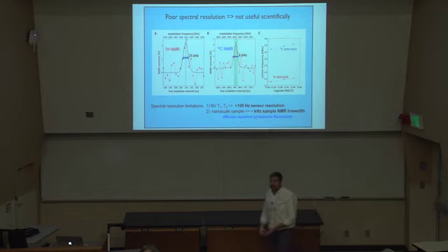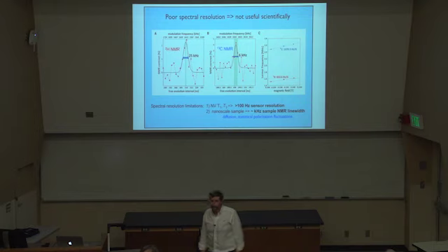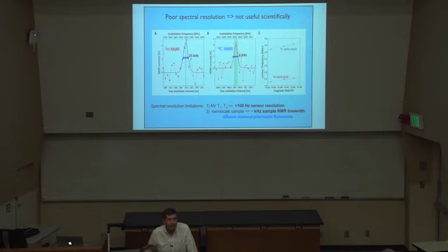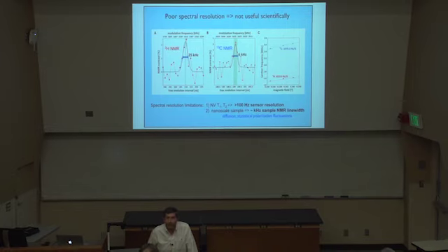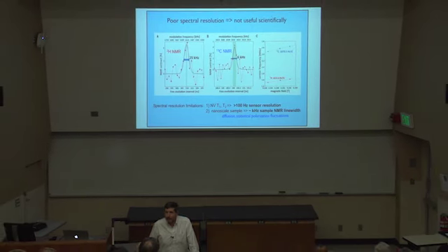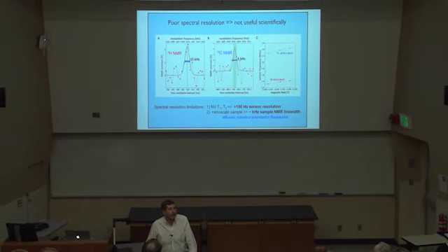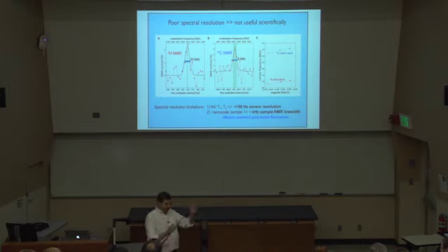You have a finite number of spins there, and no matter how well you get your thermal polarization in a strong magnetic field, part in 10 to the 5 or something like that, when you're down to tens or hundreds of spins in a protein, the square root of the number of spins, and then the 1 over that square root, will tell you what you're dealing with in terms of statistical polarizations. You can have 10% polarization fluctuations, which will dominate over the thermal polarization and basically means you're looking at a sort of narrowband noise signal, right? And that's an inherent problem at the nanoscale.